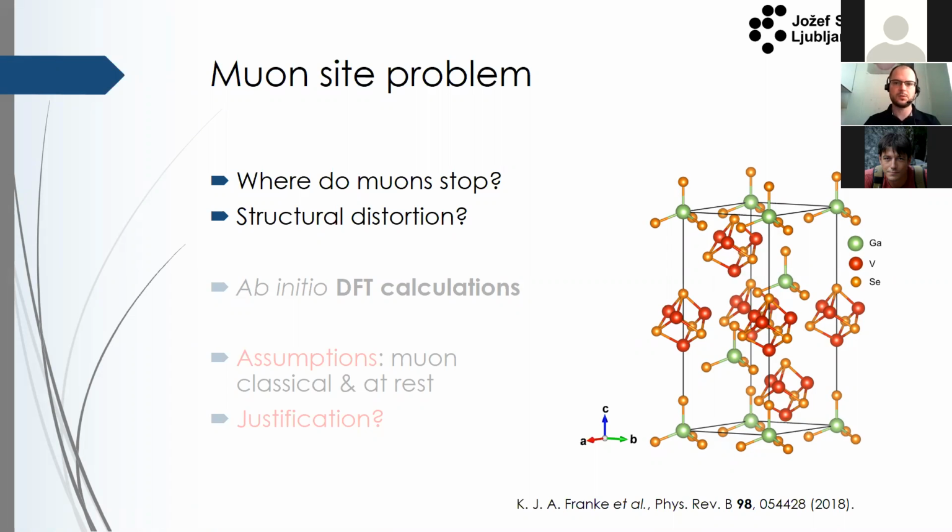So this kind of problem has been a problem of muon spin rotation (µSR) for a very long time, but it's been recently solved in the last 5 to 10 years, almost completely using ab initio DFT calculations. These are electronic structure calculations that can tell you how the electrons behave inside crystals without assuming anything. So from first principles, basically just putting in the atoms and letting the code calculate where the electrons are and where the muon would like to sit in the crystal.